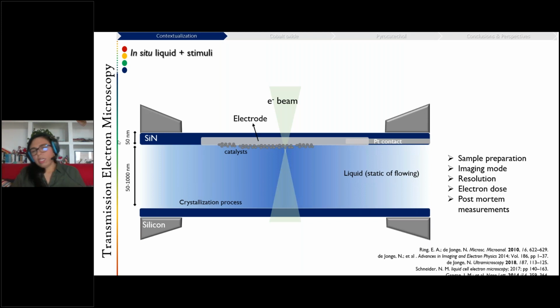So I will explain a little bit later, a little bit more about the setup, but this gives us already an idea of how our cell is constructed. So we have two silicon chips that have a silicon nitride window, in which one has an electrochemical circuit imprinted, where we have an electrode of glassy carbon, which is electron transparent, and where we can put our catalyst. And this is connected to a potentiostat out of the holder. And we can see through this silicon nitride window our material in contact with an electrolyte.